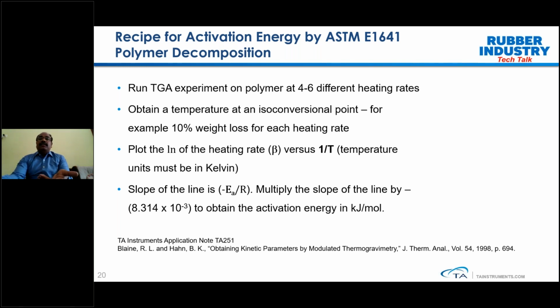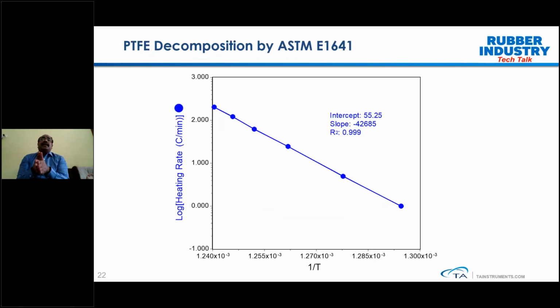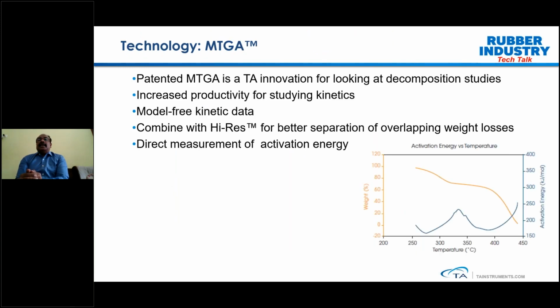But now you don't need to do this kind of study. The benefit is we have a technique called modulated TGA. The idea is how you can study polymer decomposition kinetics in a single run. As I explained, the normal ASTM technique involves multiple heating cycles, whereas in this case we don't want to perform multiple. In a single heating cycle, you would be able to calculate the activation energy. So that is called modulated TGA.